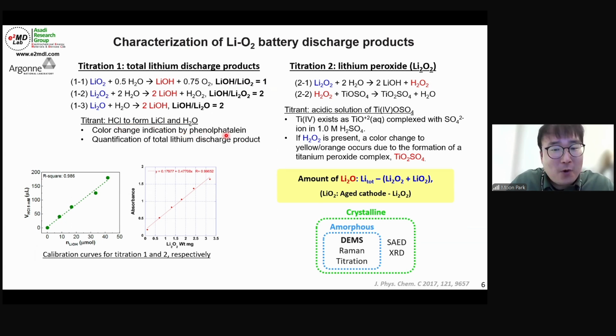By adding phenolphthalein into this solution, there are going to be color changes. We use UV-based spectroscopy to get the color difference. By comparing that amount with the pre-obtained calibration line, we can quantify the amount of total lithium discharge product. And then the second titration is a lithium peroxide titration that specifically determines the amount of lithium peroxide only.